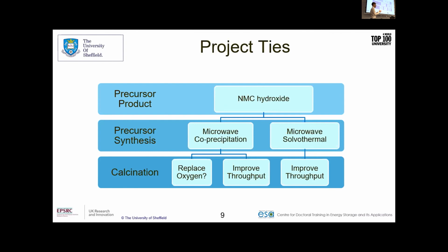We're still to analyze the performance electrochemically and optimize that side of things. But nonetheless, if we can increase the throughput fourfold, then we can produce 4 times, and then we can all buy Teslas and happy days. But yeah, the other thing I'm looking to do is replicate what I've talked about in terms of the control within the co-precipitation to form precursor with microwave conditions. So at the moment, I've started off with solvothermal, which means just putting it in a hydrothermal bomb, so high temperature, high pressure, hope for the best. And that's starting to perform a bit more control, but I'm hoping that we can translate this over to more conventional, widely used co-precipitation syntheses, so that we can produce the same sort of particles, but in a fraction of the time, just as we've seen in the calcination step.